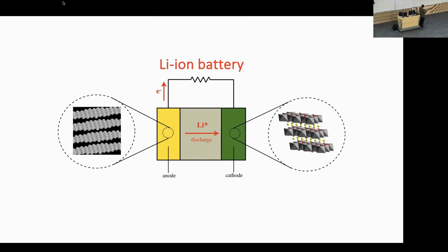But in the charged state of a battery, what you do is you move the lithium ions from these layers and insert them between the graphite layers. That way they have a higher free energy than in this state. So there's a spontaneous chemical driving force for the lithium to want to move from the graphite to this transition metal oxide to lower its free energy. But they can't do it because there's this solid electrolyte in between.